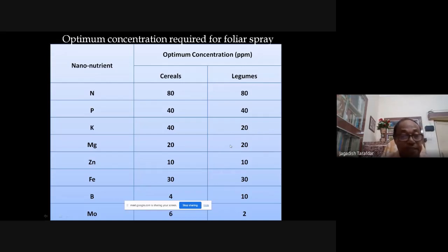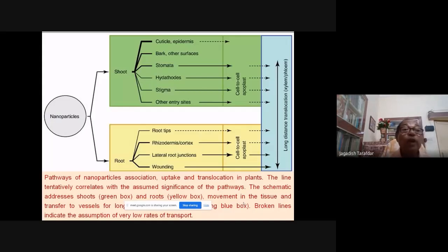Magnesium 20 is the safe limit. Zinc 10 ppm. Iron 30 ppm. Boron 4 ppm for cereals, 10 ppm for legumes. Molybdenum 6 ppm for cereals and 2 ppm for legumes. So now, when we are applying foliage, what is happening? This nanoparticle can enter through the shoot, through cuticle, stomata, hydathodes, stigma, or other structures, or through roots, root tips, rhizodermis, lateral root, and wounding. What is happening after entering?